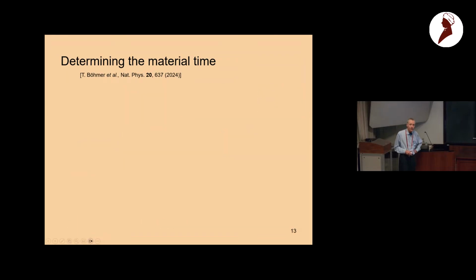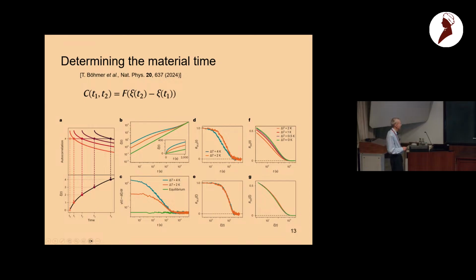And now we can actually determine the material time from the time autocorrelation function of the scattered light. So basically we assume this fundamental thing that the time autocorrelation function controls the change in material time. And then we find some level, I think 0.3 for the normalized. Here's the time autocorrelation function, and once it reaches this level, we say we have 1 unit of material time. And then we start all over at a new time autocorrelation function starting here, and it decays to here. That's 2 units of material time, and so on. In this way, we can determine the material time as function of actual time here.